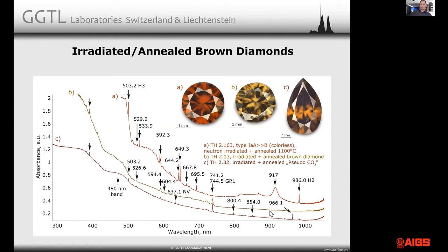The other 2 samples are to show you what happens if you treat a stone that has been brown at the beginning. That's stone number B. Stone number B was brown before treatment. Probably the dose of irradiation was not high enough in this case. It's a stone that we have treated. I think it was just 2 MeV irradiation and not long enough. And the stone was somewhat dark before treatment.